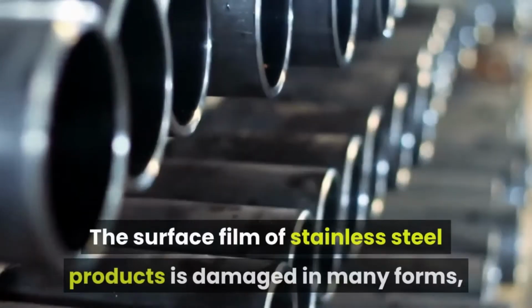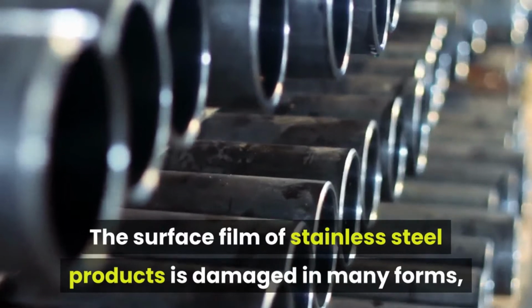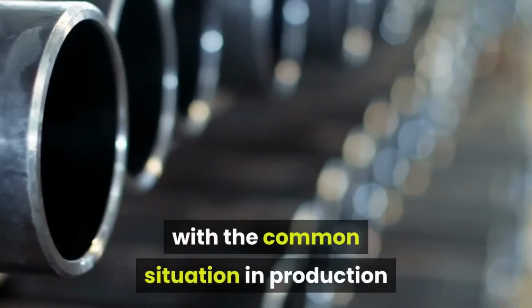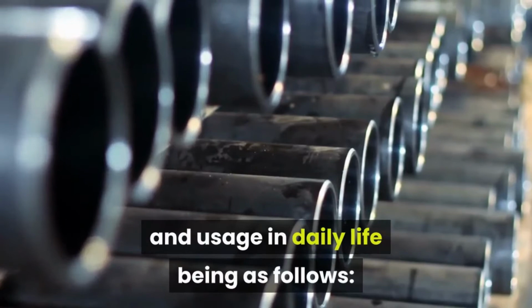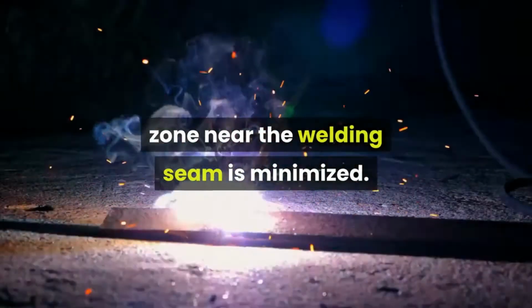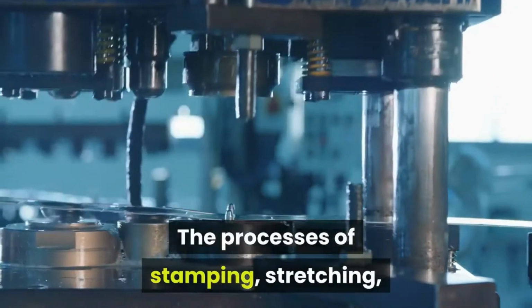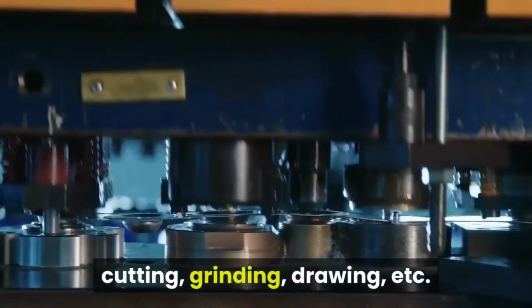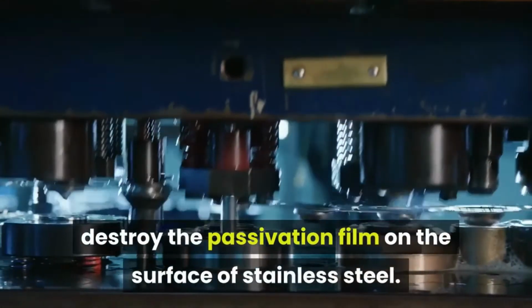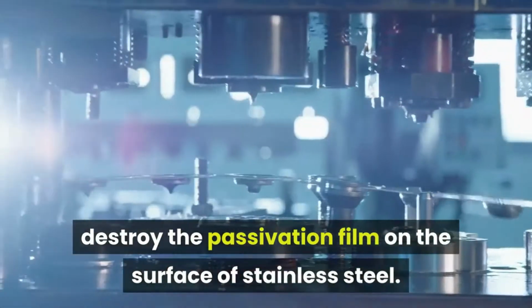The surface film of stainless steel products is damaged in many forms, with the common situation in production and usage in daily life being as follows. Due to the heat of welding, carbide precipitates in the heat-affected zone near the welding seam. The processes of stamping, stretching, cutting, grinding, drawing, etc. destroy the passivation film on the surface of stainless steel.